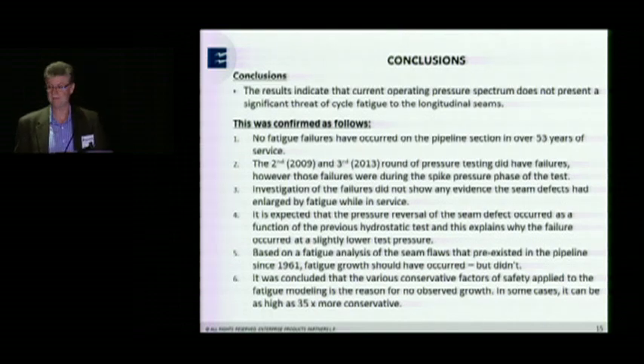And I also want, as I stated earlier, I'm concerned. In this case, we're managing this pipeline fine without testing it to over 100%. And I don't suspect that, as long as we keep a good active management program on here, we're going to see failures due to fatigue. While I love to test it to 100%, I know if I tested this line or other lines that have vintage over 100%, I'm going to start seeing a lot of failures. I'm going to be blowing up pipe in people's backyards. I'm going to have hundreds of failures. So we've got to be very careful how we define a spike test.